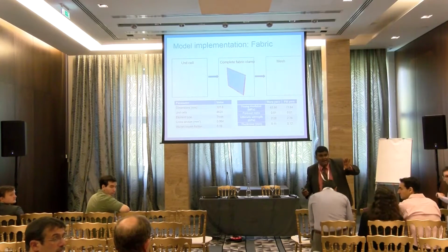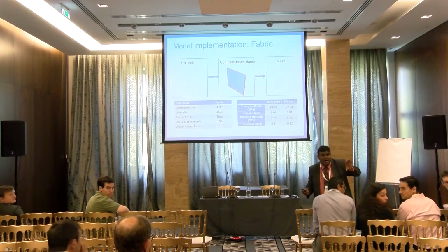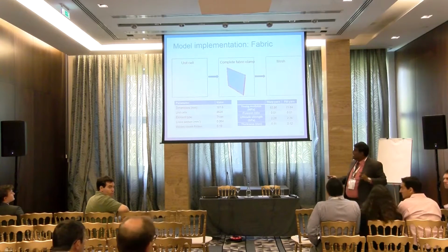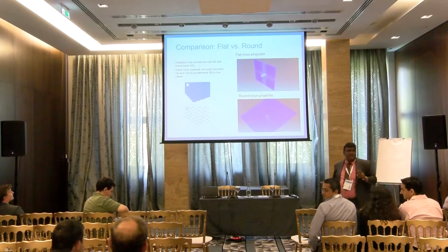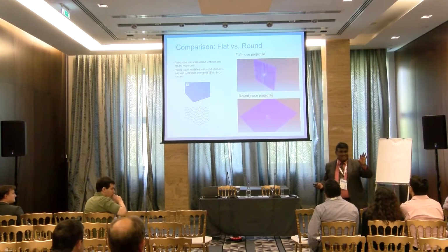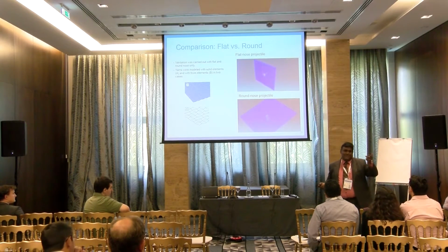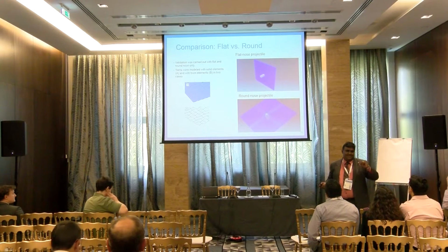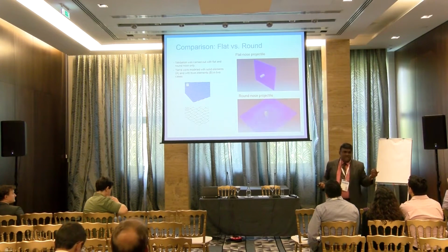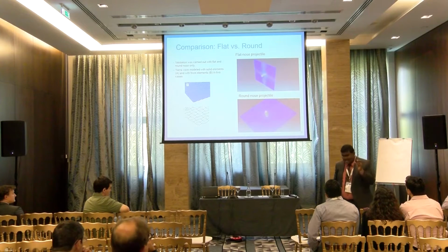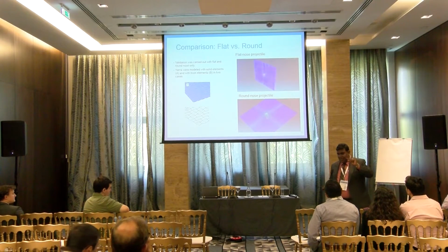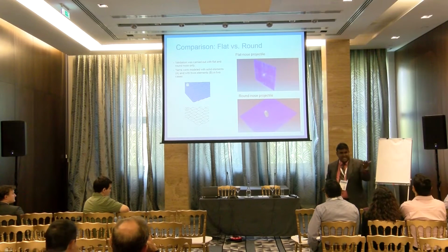About the validation, have you also compared the size of the holes in Kevlar or just the residual velocity? We compared the residual velocity and we did compare the size of the hole as well. But I would like to tell you when it penetrates, the size of the hole is very close to the projectile diameter. What we really compared was the area around the point of impact and how the holes were created by the failure of the fibers. We compared them, and it closely matches.